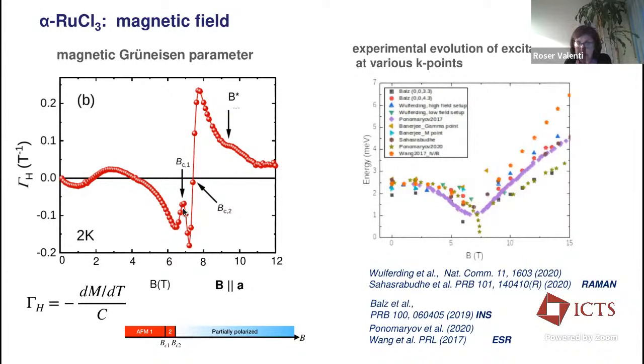This other transition here is a transition within the zigzag phase, which also has been observed in neutron scattering experiments, where the zigzag Q vector changes, and it's due to the three dimensionality. Now here, what we have plotted is, again, as a function of magnetic field, the experimental evolution of the excitation energies that have been reported in different measurements.